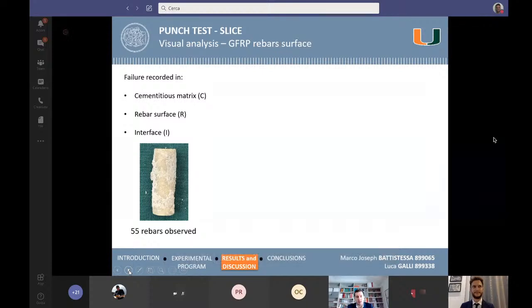Well, we classified the failure mode as failure at the cementitious matrix, failure at the rebar surface, and failure on the interface between concrete and reinforcement. In all the rebars observed, we have seen the three types of failure in different percentages.